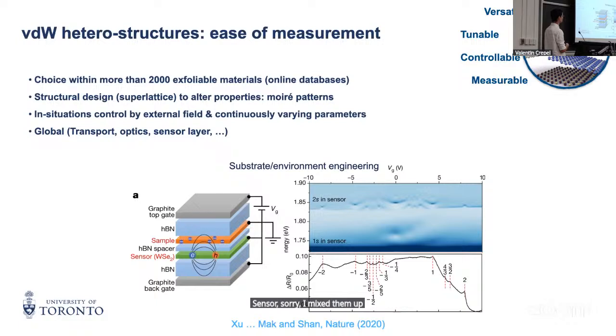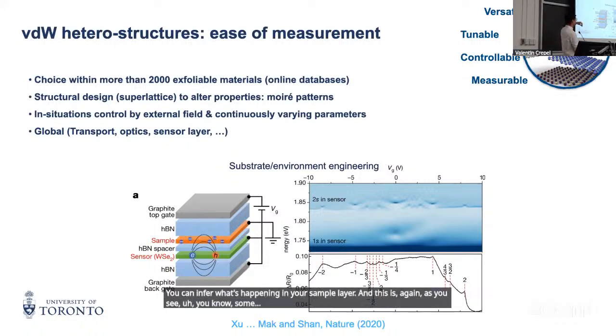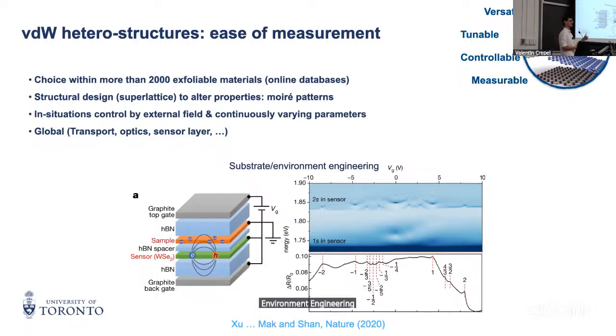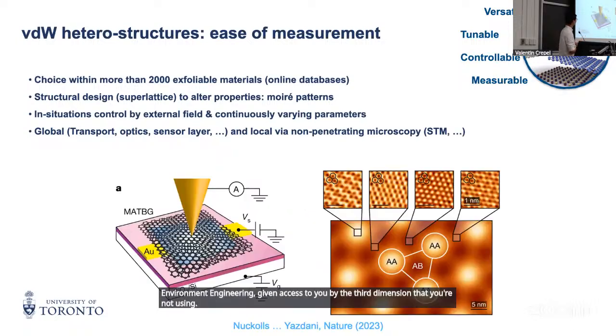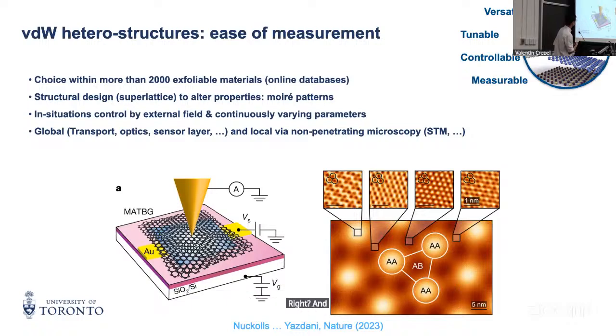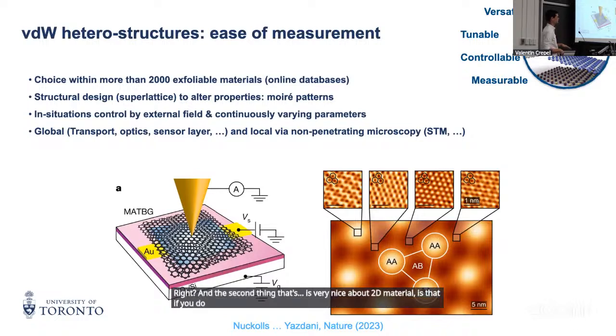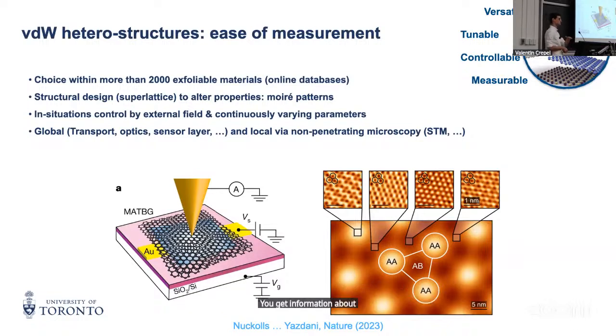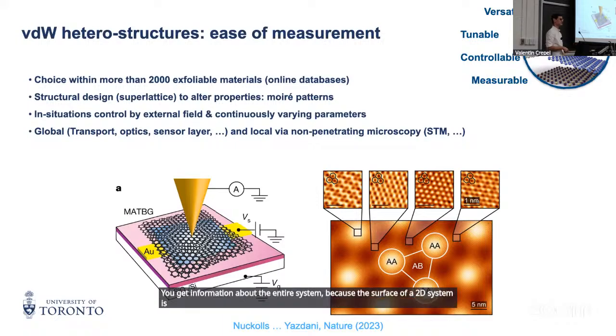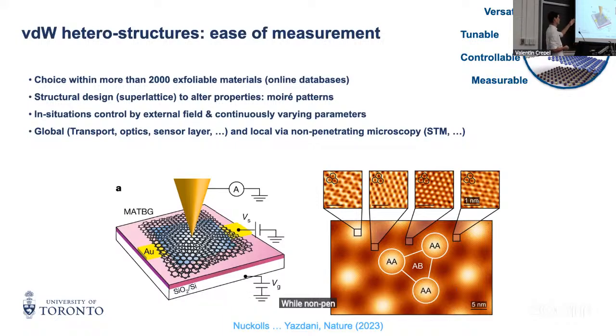But by looking at the material that you know very well, you can infer what's happening in your sample layer. And this is, again, as you see, some environment engineering given access to you by the third dimension that you're not using, right? And the second thing that is very nice about 2D materials is that if you do 2D spectroscopy, you get information about the entire system because the surface of a 2D system is the entire system. While non-penetrating microscopy, usually for bulk material, only probes defects that happen at the surface.